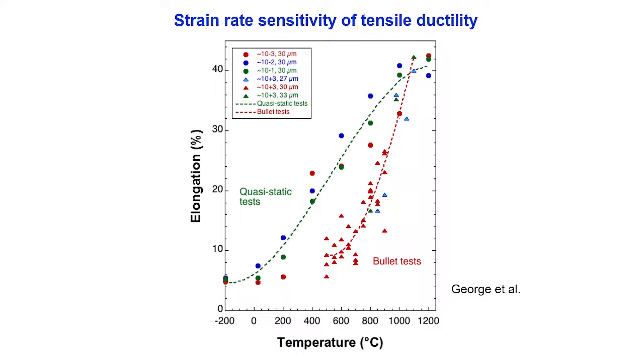The reason this high strain rate is important is because if there's an accident, this thing is going to plunge down and hit the earth at very high strain rates, on the order of 10 to the 3 per second. So this is why you have to worry more about what happens under these strain rates than this strain rate.